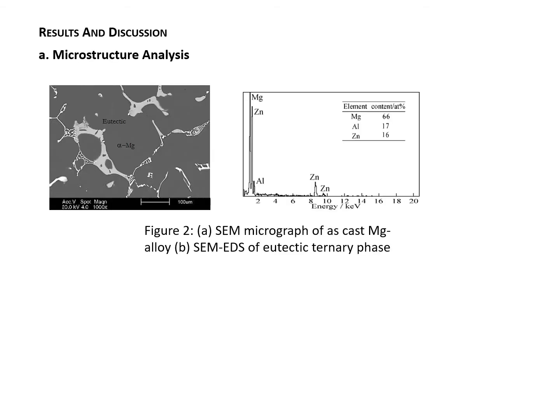Results and discussions. The first result and discussion includes microstructural analysis. The SEM micrograph of the permanent mold as cast ZA85 alloy is presented in figure 2A. From this figure, it is observed that the microstructure of Mg alloy ZA85 contains an alpha Mg matrix, ternary intermetallic phases, and gamma stable phase at the grain boundaries.